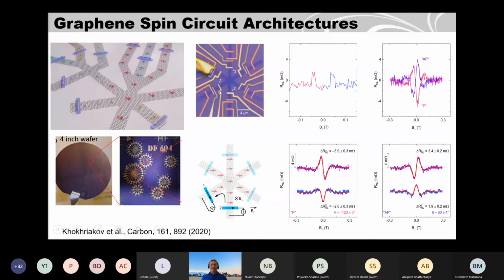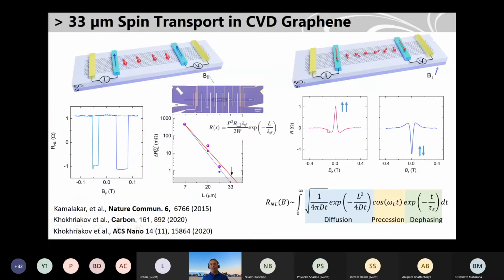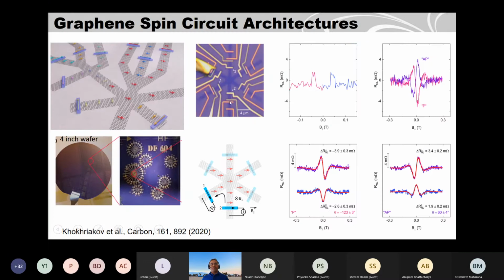And what we can see is how the spin signal develops. Because these magnets are non-collinear, if your spin goes straight, you'll get very symmetric Hanle curves, as I showed you, like this. Very symmetric Hanle curves. But if you detect the spins at an angle, let's say 45 degrees or 60 degrees, then you will see the asymmetric components.